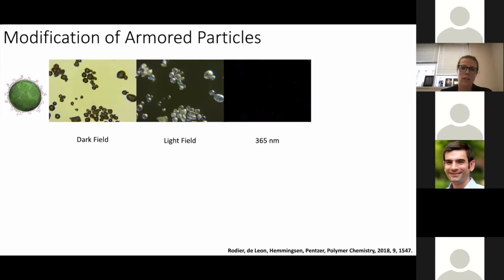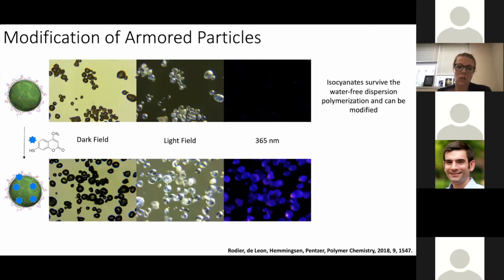And so here Brad's taken these solid polymer particles and seen if the isocyanate groups are accessible. And so he chose to functionalize them with this thiol functionalized coumarin dye. He could then get the addition of the thiol to the isocyanate and show that he could homogeneously modify the particles. And so we knew the isocyanates survived because we're in a non-aqueous environment.